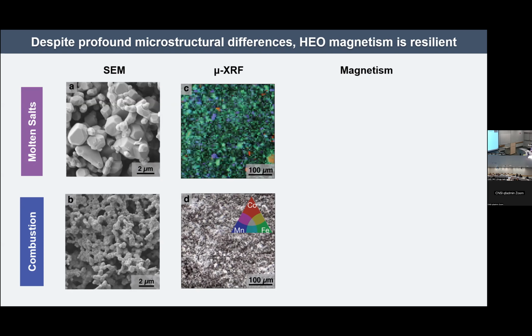I just want to clarify that compared to that atom probe measurement I showed you on my first slide, where we had all those pixels as the atoms were evaporating, a method like that is not quantitative in the same regard. So this sample would still look homogeneous if we did this atom probe tomography. It's not that these elements are missing in any region, it's just that they're in non-equal stoichiometries.